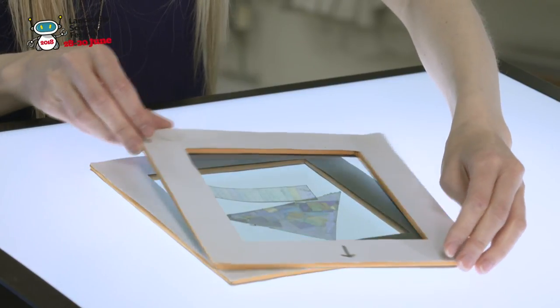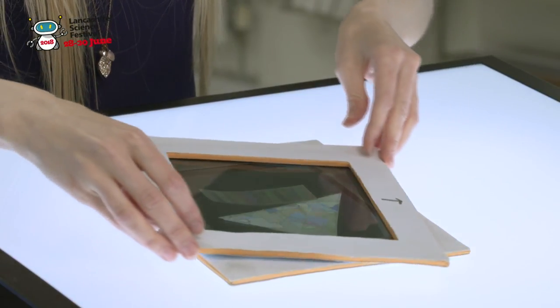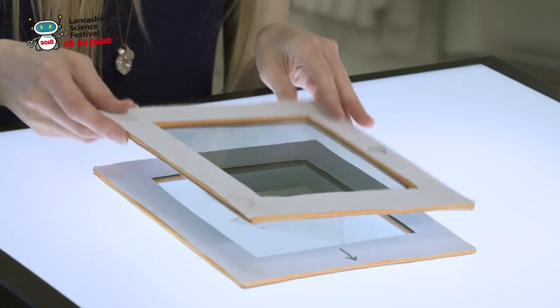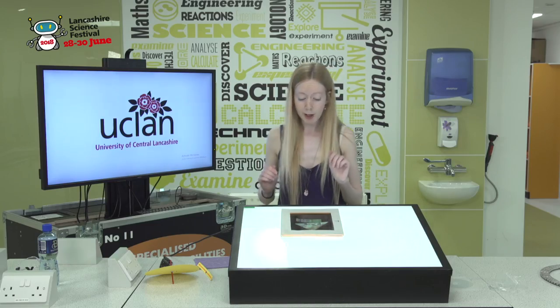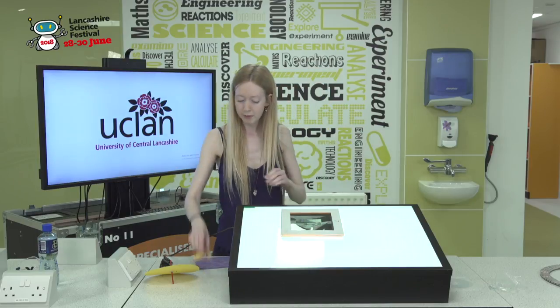So as you turn it around, you get all these different colors appearing on the sellotape. So that's because sellotape can actually change the angle of our polarized light. So we've got a polarized light like this, and it twists the angle of it. And that depends on the thickness of the sellotape and what angle you've put it on and various other things. And so the end result is that you get all these really cool colors.